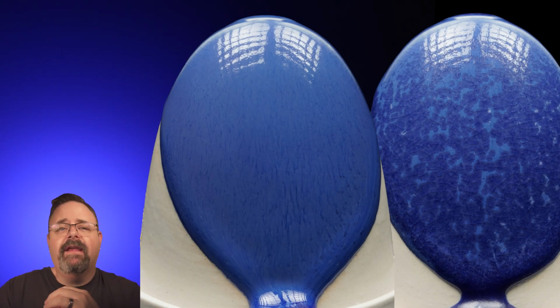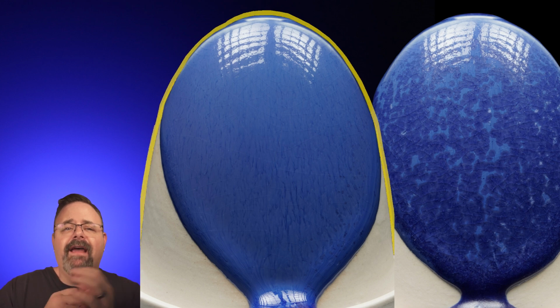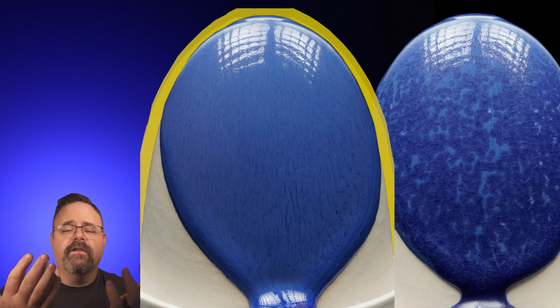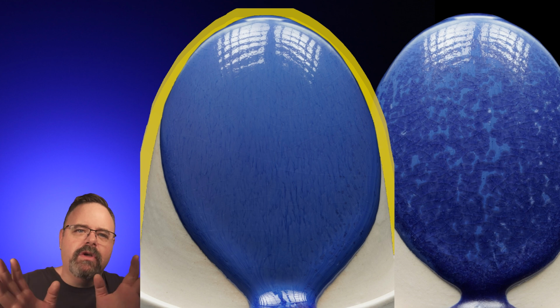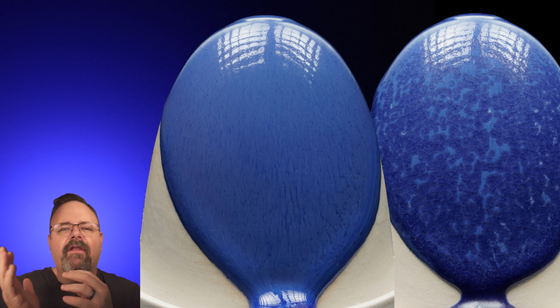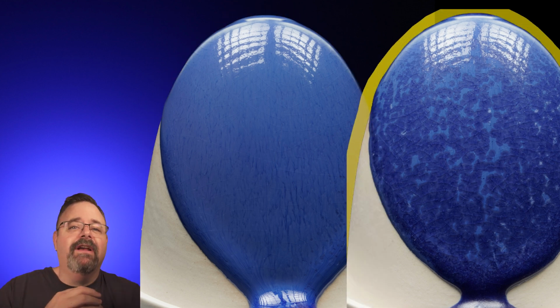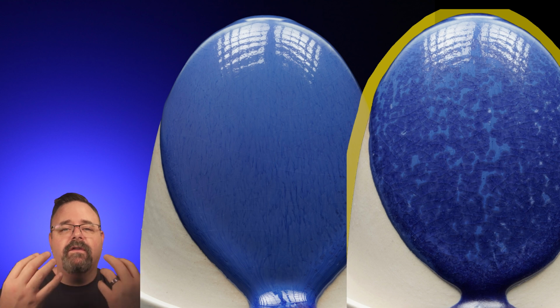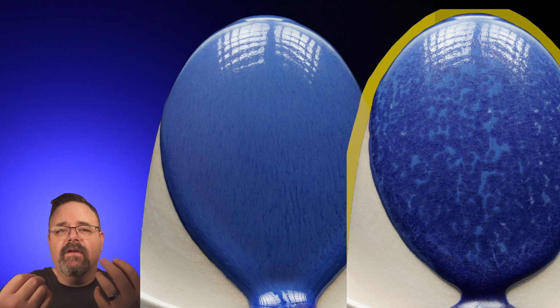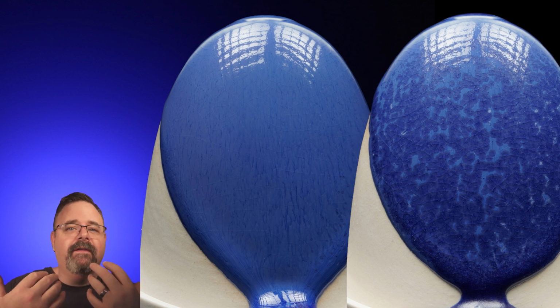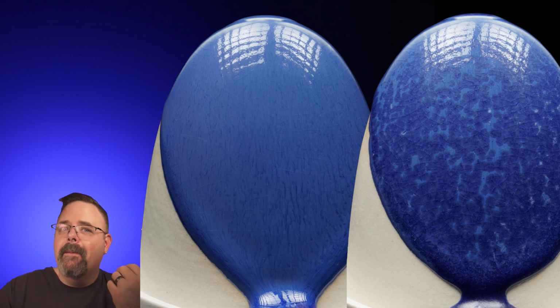And we can see that here. Here's another crystalline glaze. On the left is a natural cool, and there's no crystals to be seen. They're actually there, but they're so small you can't even see them. And then on the right is the exact same glaze, just in a slow cool, allowing those crystals to blossom and bloom as it goes through the firing cycle. Again, one of those things that will benefit. As I said earlier, matte glazes do not care about slow cooling. Crystalline glazes 100% care about slow cooling, and so making sure you're treating the glaze correctly is going to make a major difference in how that glaze performs.